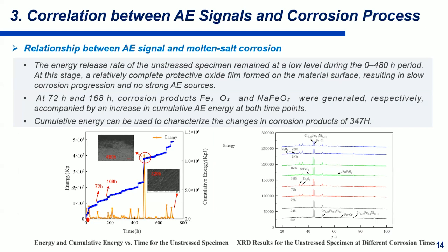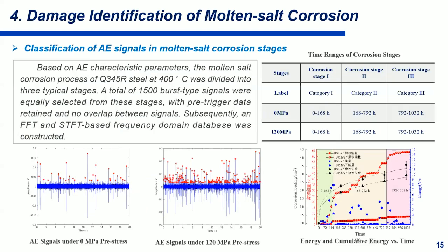And when we check the relationship between the AE signals and the molten salt corrosion, the energy release rate of the unstressed specimen remained at a low level during the 0 to 480 hours period. At this stage, a relatively complete protective oxide film may form on the material surface, resulting in slow corrosion progression and no strong AE source. At 72 hours and 168 hours, corrosion products, ferrite oxides and sodium ferrite oxides were generated respectively. Cumulative energy can be used to characterize the changes in corrosion products of 347H stainless steel.